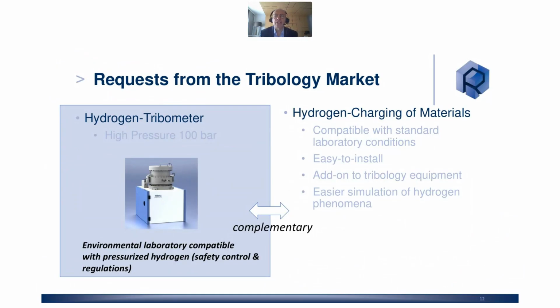The idea behind the development at EPFL is really to have the possibility of testing with hydrogen charging of material. The big advantage is that the cell is small, so it's compatible with standard laboratory conditions. It is possible to install it on an existing tribometer and to make simulation of hydrogen phenomena easier, meaning that you can create hydrogen embrittlement in material on a relatively simpler setup and already do advanced studies on hydrogen embrittlement with a tribometer. Of course, these two ideas are complementary. It does not mean that we'll replace the whole hydrogen tribometer, but it has a big advantage to be able to do testing under hydrogen in a standard laboratory without strong safety regulation.